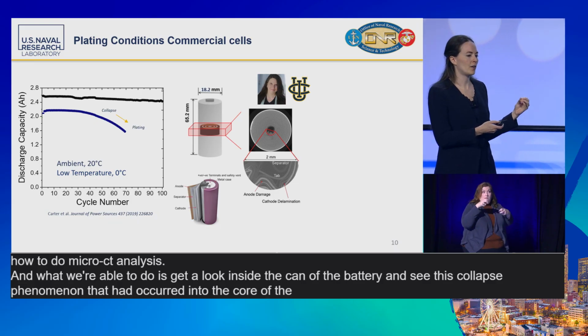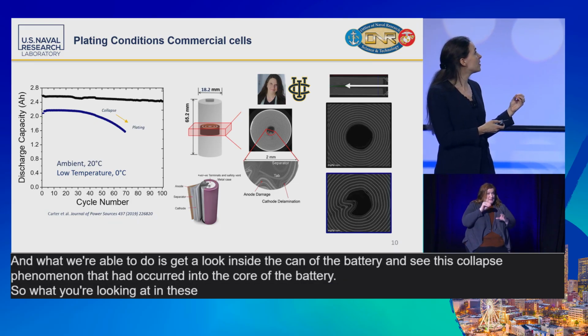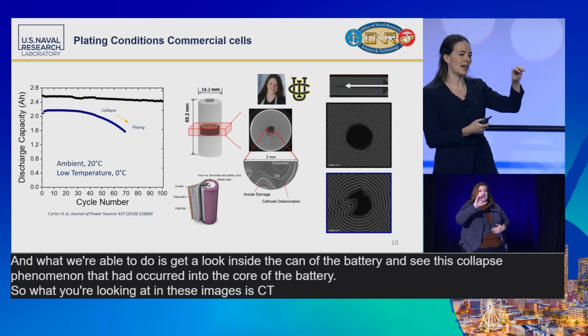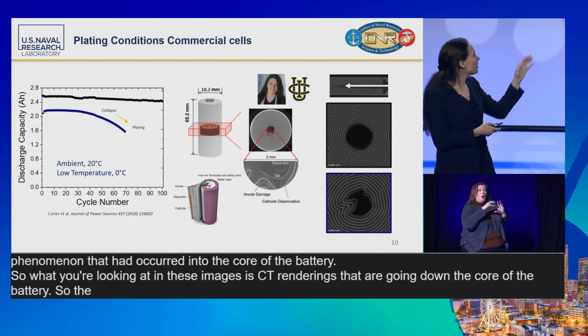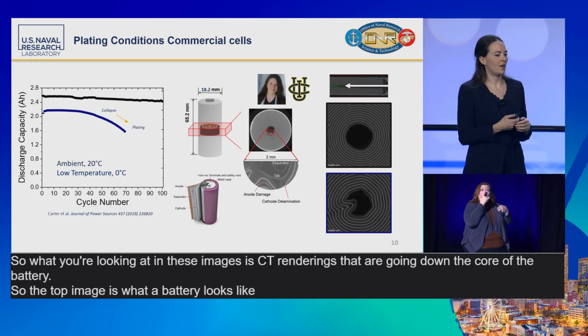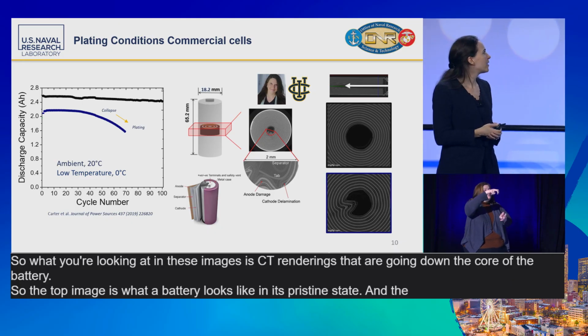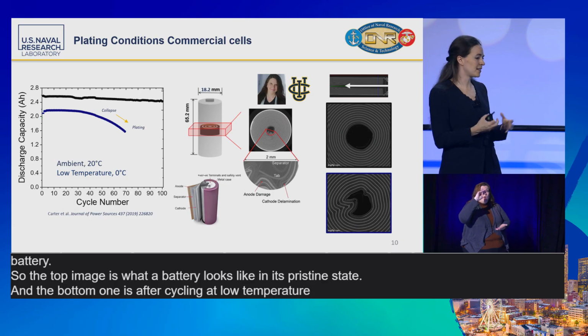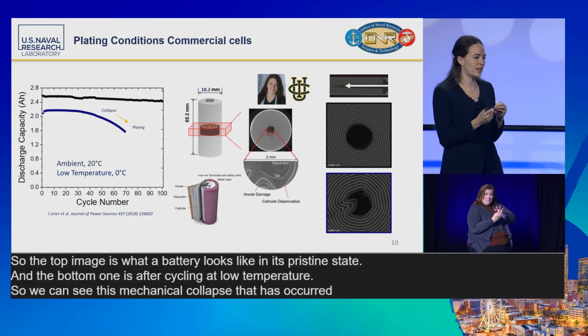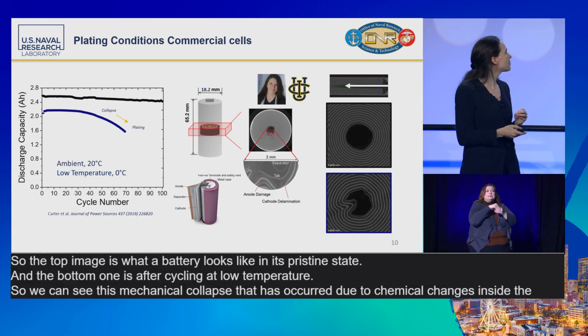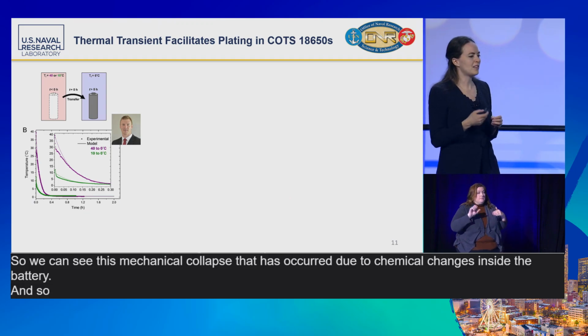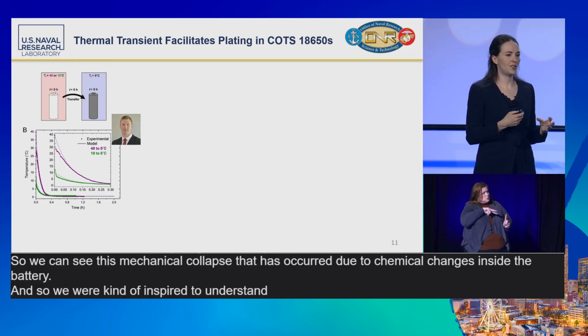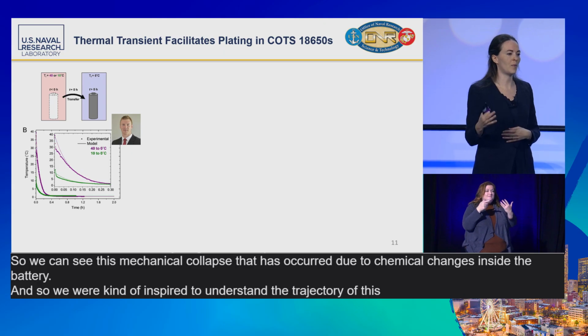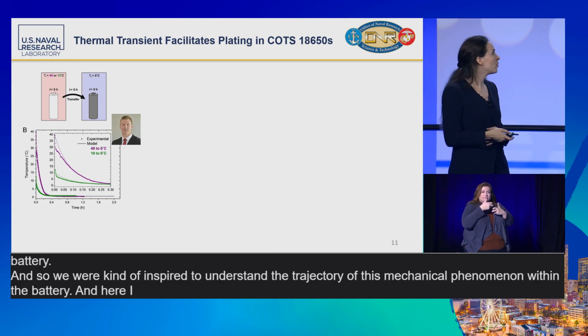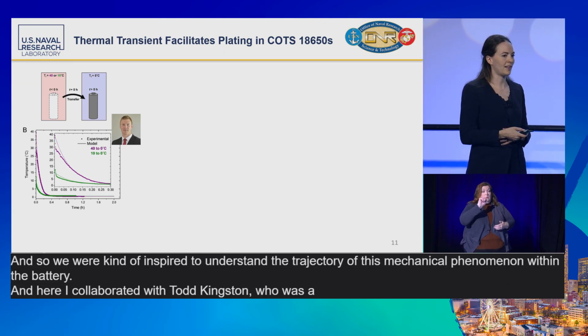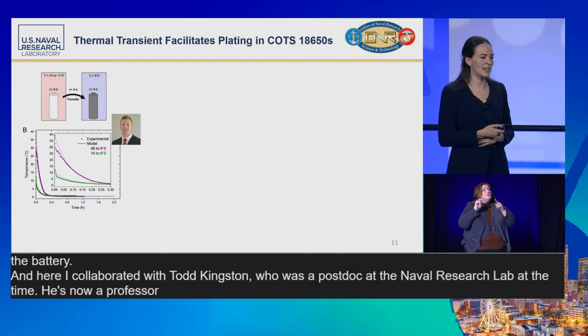So what you're looking at in these images is CT renderings that are going down the core of the battery. So the top image is what a battery looks like in its pristine state. And the bottom one is after cycling at low temperature. So we can see this mechanical collapse that has occurred due to chemical changes inside the battery. And so we were kind of inspired to understand the trajectory of this mechanical phenomenon within the battery. And here I collaborated with Todd Kingston, who was a postdoc at the Naval Research Lab at the time. He's now a professor at Iowa State.